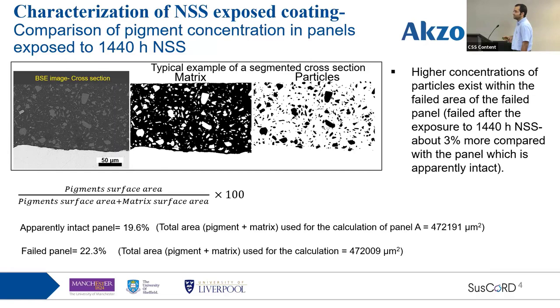So 3% will mean that we are either above the percolation threshold or below the percolation threshold. And actually, we have clusters of connected particles formed within the coating, or there are no clusters within the coating, and that can affect the performance.